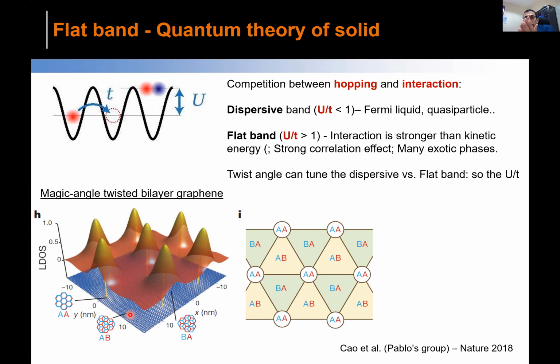So because there is a relative angle, the stackings are different at different places, and that's the periodic structure we are talking about, the superlattice. Now it turns out wherever you have the AA stacking, where you see exactly the two structures on top of each other, the density of states is higher compared to the AB structure.